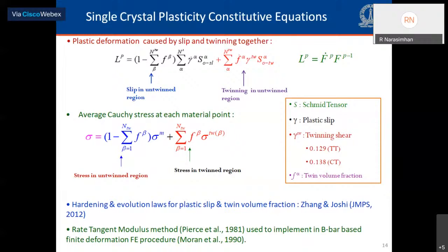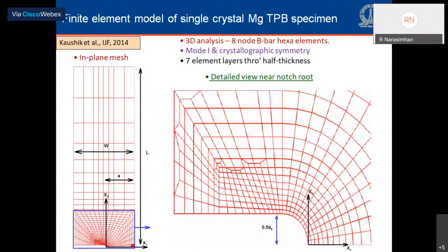And we implemented this model in our own in-house finite element code using the rate tangent modulus formulation of Pierce, Asaro, and Needleman. We implemented this within the framework of a finite deformation, B-bar based finite element procedure to treat nearly incompressible deformation in the fully plastic range.